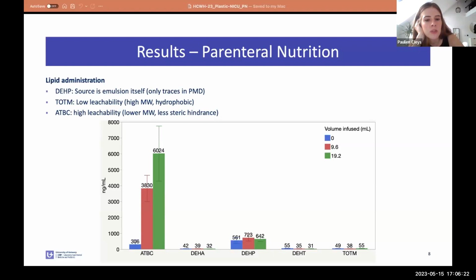Our results show that ATBC was present in high concentrations in the pressure sensor discs used in both the non-lipid and the lipid circuits. And it was also the main plasticizer in the extension set, which was used for lipid administration. So although being present in the lipid emulsion at the starting point, we see a clear increase in function of time, indicating that this compound leaches from the plastic circuit into the lipid emulsion. Then the second alternative plasticizer is DEHA, which is reported to have a very high migration potential, the highest of all alternative plasticizers. But we see this alternative plasticizer only in very low concentrations, and we don't see any real evidence of leaching in function of time.